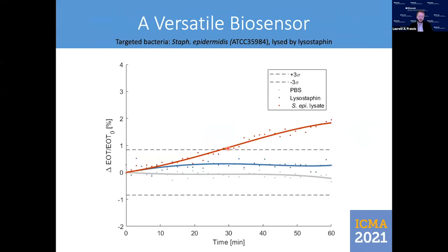Beside that, a nice feature of the sensor is the versatility. If we change the lytic agent we use, we can detect another strain of bacteria, which is the case here. So we use lysostaphin, which is the one detecting, in this case, the Staphylococcus epidermidis. And we see that we have a reaction for about half an hour because the dimension of the lysate content is probably not the same size and the same effect as in the case we had with the Bacillus cereus. Still, we have nice detection within half an hour.